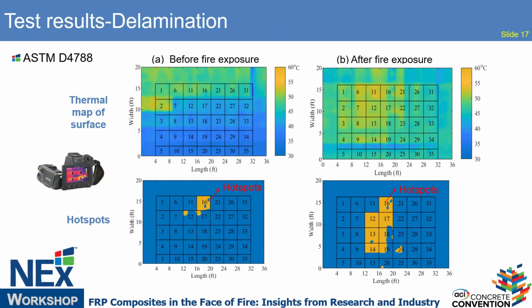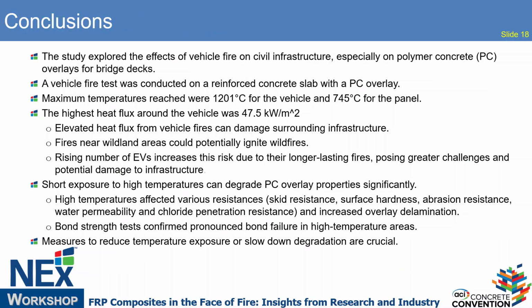So those are the delamination tests. We used the IR camera to capture the slab surface in the afternoon during the summer. Before the fire, we took the thermal image over the whole surface, and we did similar work after the vehicle fire test. We found that even before the fire test there were some hot spots, but only at location 16. After the fire test, especially in those areas exposed to the high temperature, a lot of hot spots were identified.